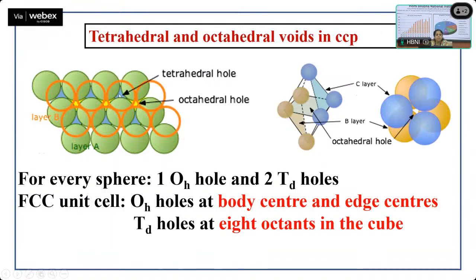Okay, that forms one tetrahedral void. Similarly, this particular atom will also contribute in a tetrahedron which has opposite orientation, that is the 3 atoms lying exactly above it. Okay, so one tetrahedron pointing downward, one tetrahedron pointing upward. So each lattice point contributes. So if I have n atoms in the close packing, the number of tetrahedral holes is 2n. For each sphere, you have 2 tetrahedral voids.